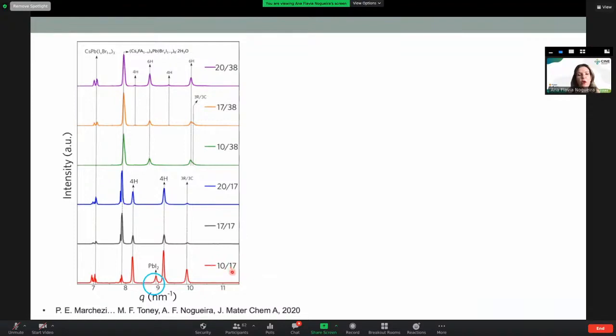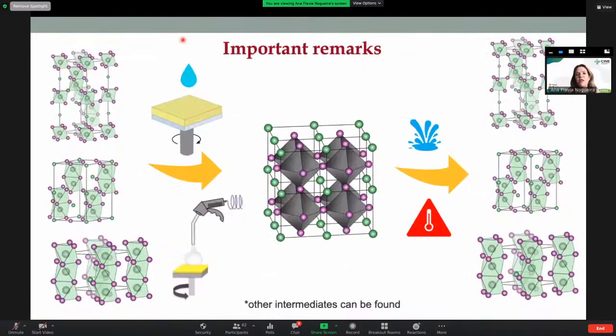For all of the samples, besides the hexagonal phases, we have this hydrated perovskite, that's actually that microrod that is really forming there. So the conclusion here, I think, from my talk is that these hexagonal phases are there during the formation of the perovskites, because they are then converted to cubic perovskites. And they are also the phases that appear with degradation. So I think here we need to learn more about how to control them if we really want to go to more efficient devices.